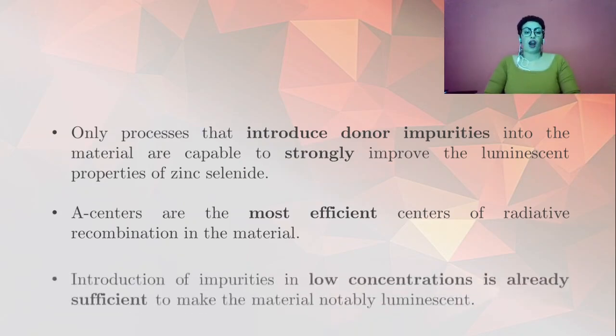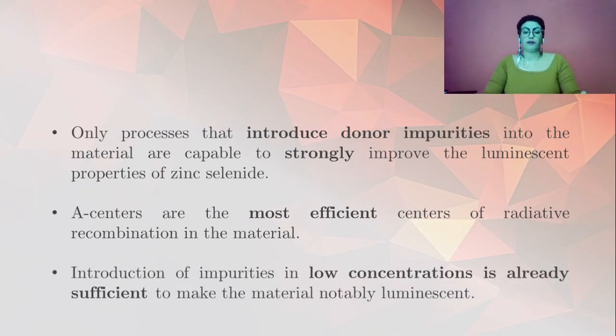This work also indicates that the introduction of impurities in low concentrations is already sufficient to make the material notably luminescent. Thus, the needed introduction of impurities to increase the luminescence of the material may not compromise its application as a scintillating bolometer, since the low detection background achieved in the experiment can be easily maintained by correction once the impurity and the concentration is known.